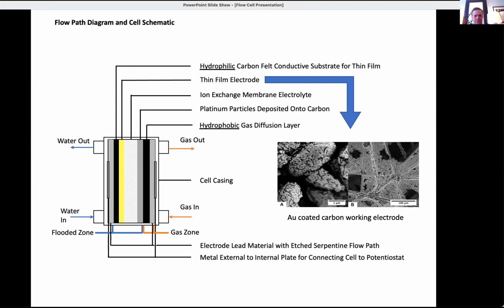You have an electrolyte, which is a requirement for here, but it's a solid state polymer membrane. And we use platinum nanoparticles deposited on carbon as our electrode, which can act as both the reference electrode and the counter electrode, where water is split on the regeneration cycle. And it does need a reference gas here. The reference gas can be supplied from a second smaller electrolysis cell, which is built on similar technology, which just takes water and generates a very low